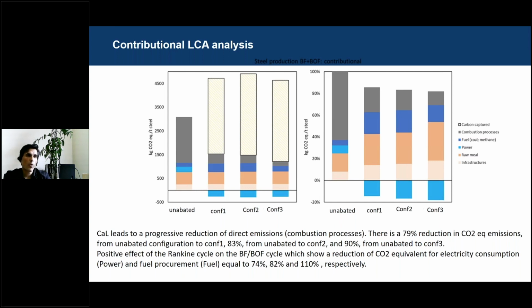As you can see, also with the increase of integration of calcium looping into the steel mill, we have a progressive reduction of direct emission. In fact, there are values of 79, 83, and 90% with the increase of the level of integration.